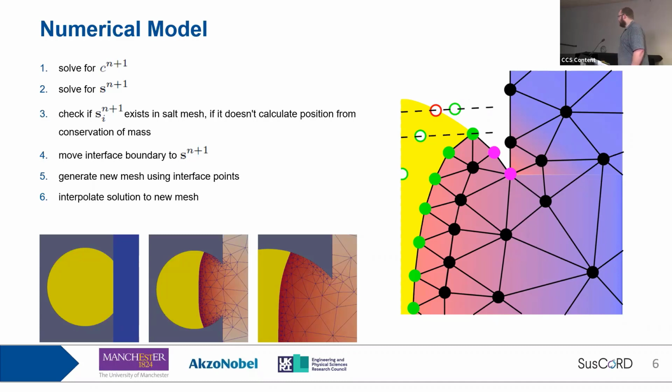Okay, thanks very much, Joe. It's really good. Just before we clap, I'll make one comment. There are two aspects to this model which may need adapting, I think. One is that the particles are treated as rigid, essentially, in other words absolutely defined, whereas in fact they're more likely to be fuzzy, in the sense that there is water within the matrix as well. The second point is that diffusion of water is maybe 10 to 100 times more rapid along that boundary. So you'll get diffusion at the back of the particle, but I know you've been adapting the model for those things, and I thought it was a fantastic talk. Thank you very much.